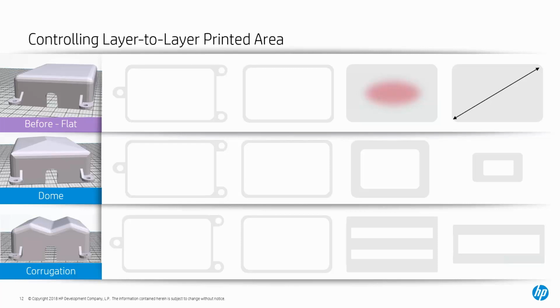But if we move across and we look at it layer by layer as the part would start to print, and we look at the thermal map of the part, we see as we get to the flat part of the top of the housing, there would be a rather large warm area that would happen inside of this part, which would make the part shrink and contract and bring the parts in, which could potentially cause a warpage issue. So if you start thinking about what my part would be like in layers, and thinking about a heat map as you would slice the part, you can change your design in order to avoid that, which gives you better parts.